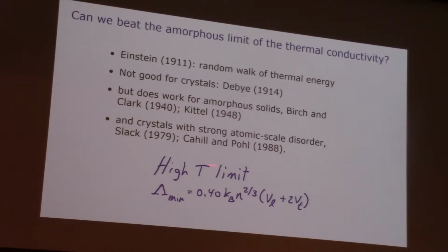And the high temperature limit of this sort of picture from Einstein, as further developed by others, is basically this. This is what we call the minimum thermal conductivity, or amorphous limit of thermal conductivity. It's a numerical factor, k Boltzmann. I'm talking about heat, there better be k Boltzmann in the equation somewhere. n to the 2/3, that's the number of atoms to the 2/3 power per unit volume, and the average speeds of sound, longitudinal, transverse, right? So basically no free parameters, you just plug it in and you go.